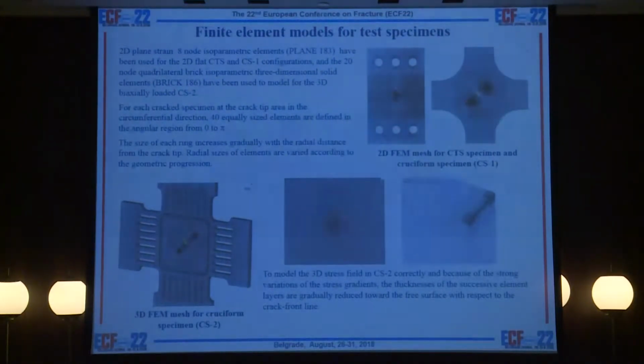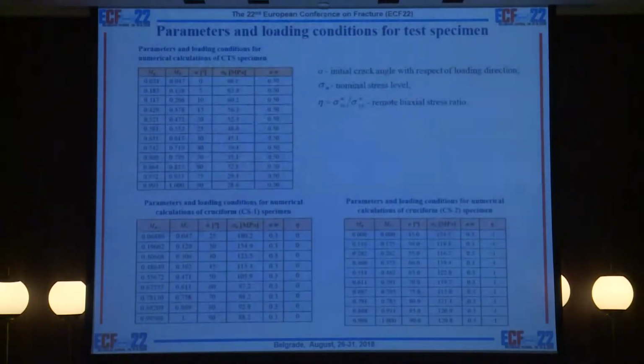In this figure, you can see the finite element models of considered test specimens. In the case of a compact tension specimen and a flat cruciform specimen, we used plane strain 8-node isoparametric elements. And in the case of the cruciform specimen with finite working area, we used three-dimensional 20-node isoparametric elements. In this figure, you can see parameters and loading conditions for all considered specimens.